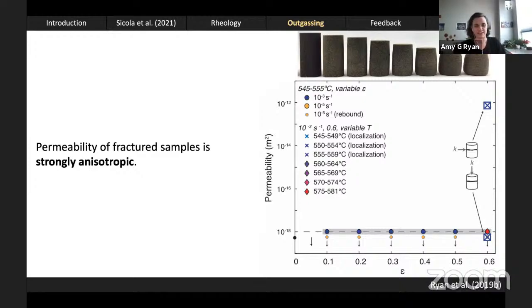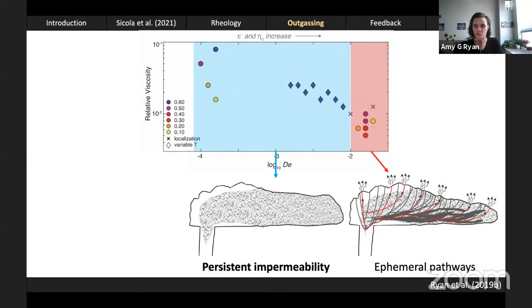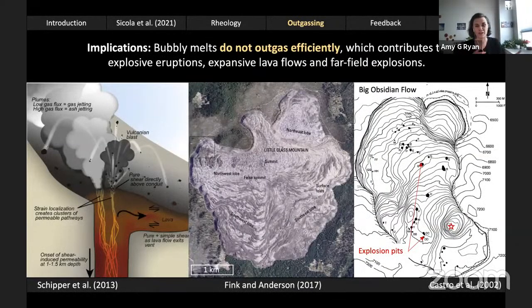I'm going to return now to my Deborah number figure and plot on there the outgassing regimes that I've observed based on these experiments. So on the right, I observed ephemeral pathway formation by melt fracturing. This model I introduced earlier only occurs, as I said, at Deborah numbers greater than 10 to the minus 2. But a majority of my samples remained impermeable across a wide range of flow conditions parameterized by the Deborah number. So what I would put forward is there was a previously unrecognized outgassing regime wherein the bubbly melt is persistently impermeable and no outgassing occurs. This really underscores the fact that bubbly melts have a hard time outgassing efficiently, which contributes to more explosive eruptions, to these expansive lava flows, and to the potential for far-field explosions.